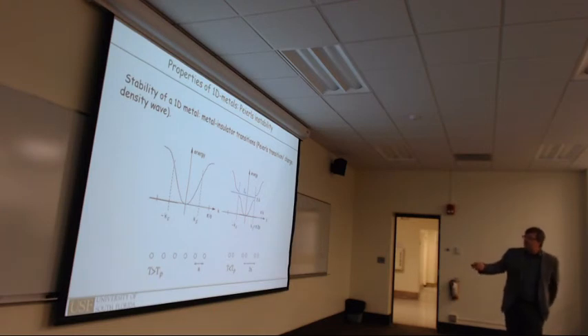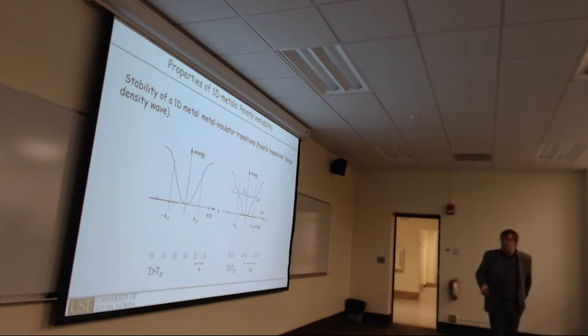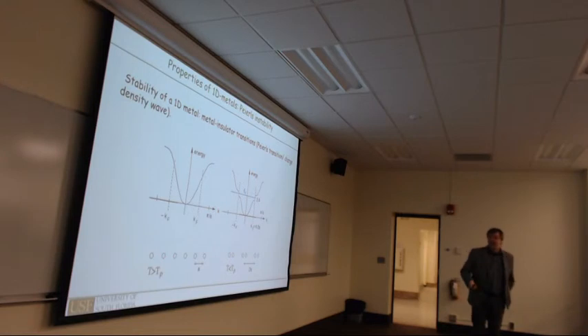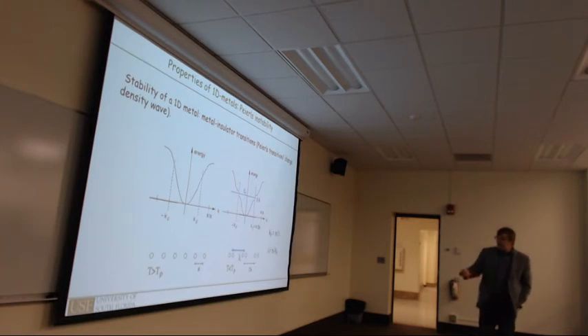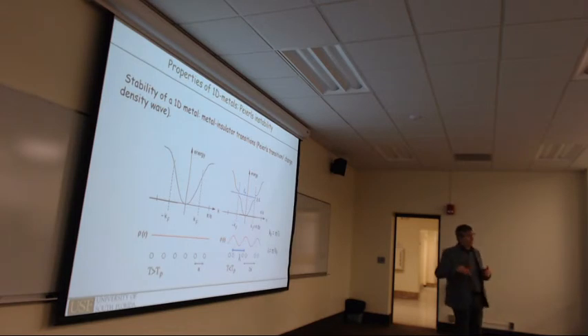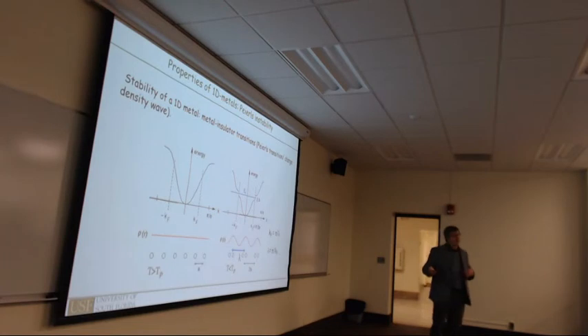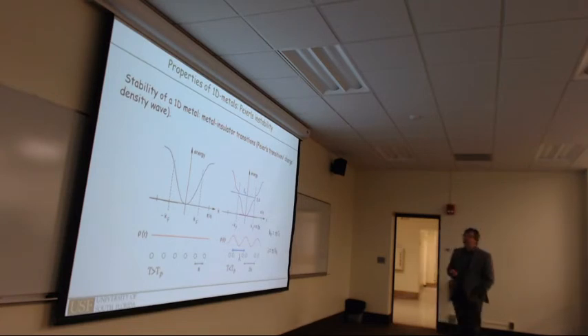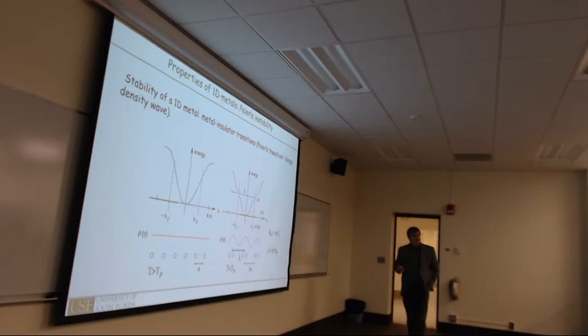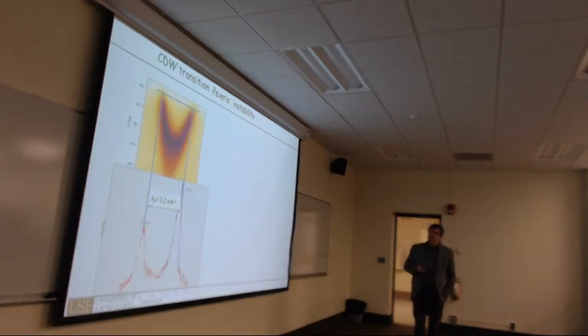The question is, how do you move the Brillouin zone boundary from pi over a to pi over 2a, for example? That you do by distorting your atomic chain and inducing a new periodicity of 2 times the lattice constant. So then in real space you would have a new periodicity, say lambda, and this lambda is directly related to the Fermi wave vector by pi over kF. And because of the distortion of the lattice, you get a modulation of your charge distribution. That's why Peierls distortion in one dimension is also equivalent to a charge density wave you sometimes observe in two-dimensional materials. So the question is, do we observe such a charge density wave or Peierls distortion in these grain boundaries?